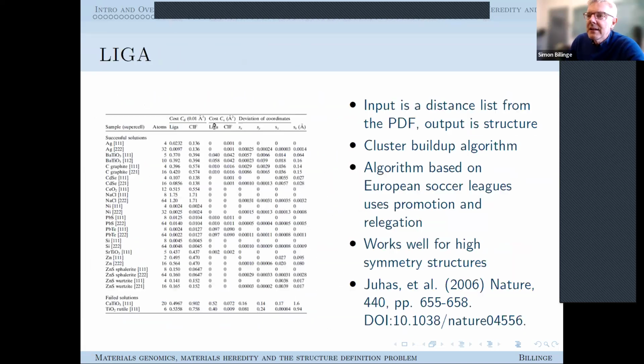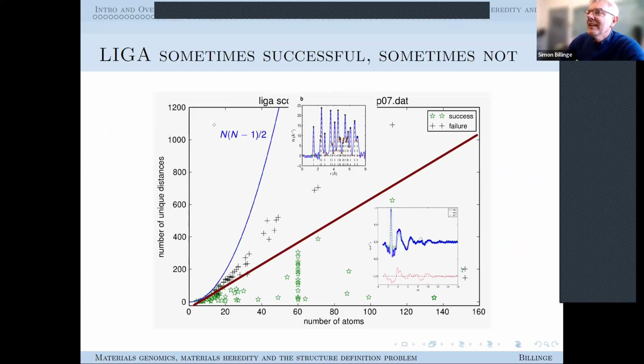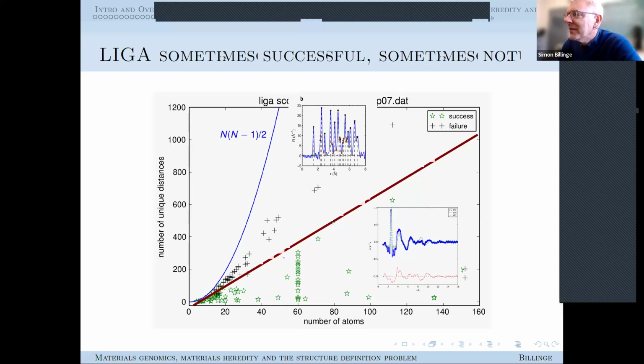So if I go back to this, actually, I have these inverted, sorry about this, but the ones that have low symmetry, their measured PDF looks like this. And the ones that have high symmetry, their measured PDF looks like this. And so it turns out that actually it's not a problem of the algorithm, that the algorithm can't solve those. It's a problem that the information content in the data is insufficient to constrain a correct solution.